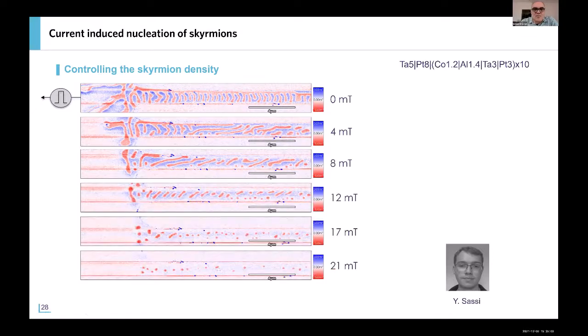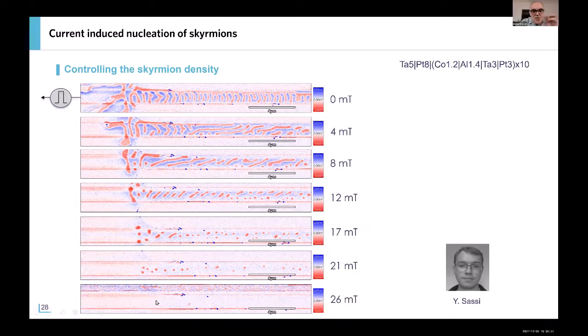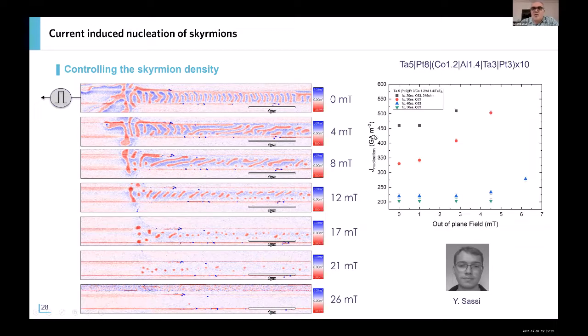Okay, so these are MFM images. You see here a track, and this is a configuration that can be imaged at different perpendicular fields after a pulse injection. You see clearly that the density of skyrmions, or even the transition from, let's say, stripe domain to skyrmion, depends on the field that you apply, and for a large enough field, we can even have individual skyrmions that can be stabilized. So we could plot the minimum current densities that need to be injected in the layers to stabilize the skyrmions, and we can control also this minimum current density by applying a perpendicular field.